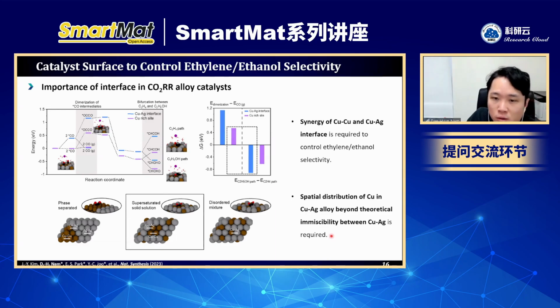Oh yeah, what I mentioned the first time is that in general, if we mix the metal with other elements, it can be phase separated, or it can be a disordered mixture. It means that elements are dispersed uniformly, or they can be totally separated. In this way, there can be a limited number of copper-silver or copper-rich sites. Copper-rich site means the interface between copper and copper, and copper-silver means the interface with copper and silver. As we know, because this intermediate dimension is very small, it is very important to design the number of interfaces between them. So the result of this calculation is that we need both copper and copper-silver simultaneously.